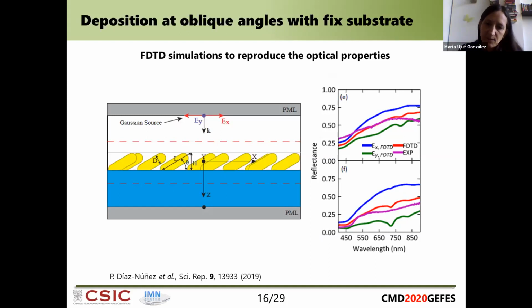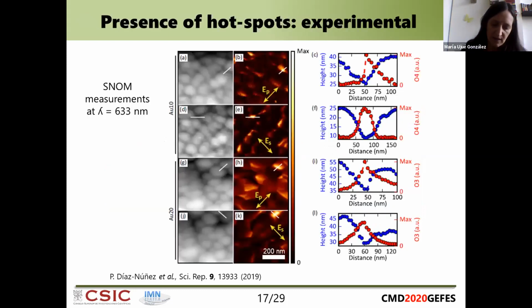And well, first we tried to reproduce the reflectance of our system with the simulations. And as you can see here, this purple line is the experimental data, unpolarized, and the red one is the FDTD simulation also for unpolarized light. And you see that the results are not so different. So we think we can get a little bit of insight on the behavior of our structures using our FDTD simulations. So as I said, we were trying here to know about the possibility of having some SERS enhancement with these very simply fabricated coatings.